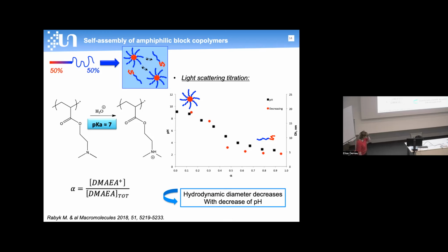So then we studied the self-assembly of this copolymer in water, and we first show that there is an aggregation to disaggregation system, which is tuned by the pH, by the addition of an acid. So here it represents the ionization degree of the dimethylaminoethyl acrylate, the amine units, and which is an on-off system, depending on the alpha. And what is very important is that it's completely reversible when you increase the ionization degree.